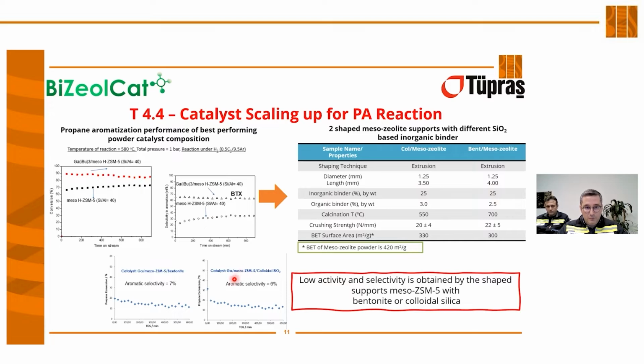When we look at the reaction performance, it was very, very low compared with the bare catalyst in powder form. So low aromatics selectivity was obtained by the shaped support for the mesozeolite with bentonite or colloidal silica.